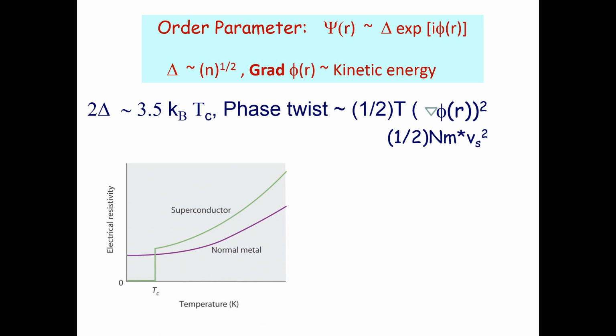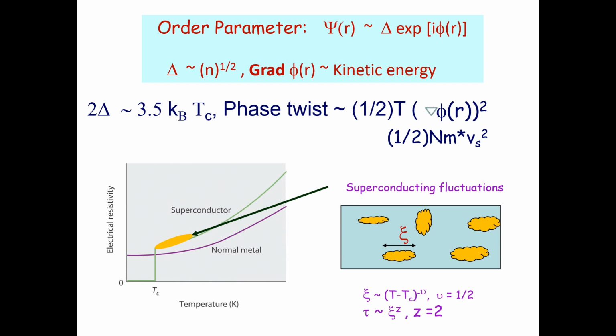But now, if I look at the bulk material like niobium once again, so this is my superconducting transition, and we know about fluctuation effects. So even before I reach Tc, there is action in this temperature range. That's the so-called fluctuating regime, where you have electrons talking to each other, pairing over a length scale xi, or you can say that you have these superconducting puddles forming somewhere here. And the size of this interaction, the correlation length, diverges as you approach Tc, becoming the size of the sample. So the whole sample becomes covered by these puddles, and the whole sample becomes superconducting.